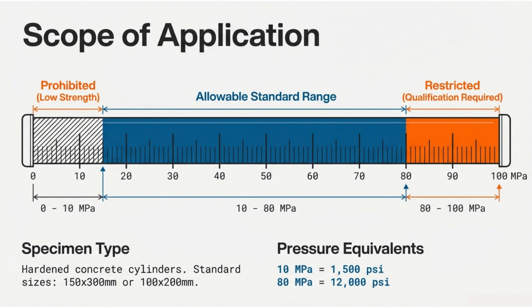In the middle zone, 10 to 80 megapascal, this is the standard range where unbonded caps are commonly used. Above 80 megapascal, you're entering higher energy failures and higher sensitivity to alignment and pad stiffness. That means qualification is required. Also note the specimen types and sizes listed. Hardened concrete cylinders, standard sizes like 150 by 300 millimeters and 100 by 200 millimeters. And the slide also reminds us of the pressure equivalents. 10 megapascal, approximately 1500 psi. 80 megapascal, approximately 12,000 psi.